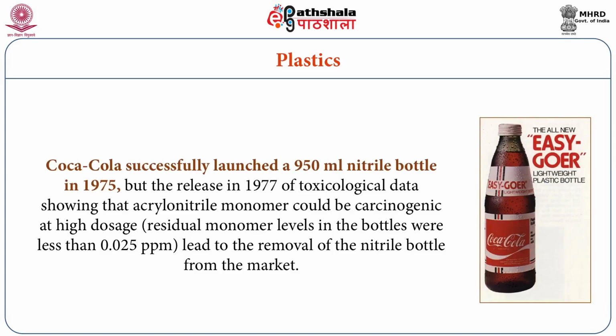Plastic bottles. The Coca-Cola Company earlier launched a 950 ml nitrile bottle way back in 1975, but the release of toxicological data in 1977 showing that acrylonitrile monomer could be carcinogenic at a high dosage, and the residual monomer levels in the bottles being around 0.025 ppm, led to the removal of the nitrile bottle from the market.